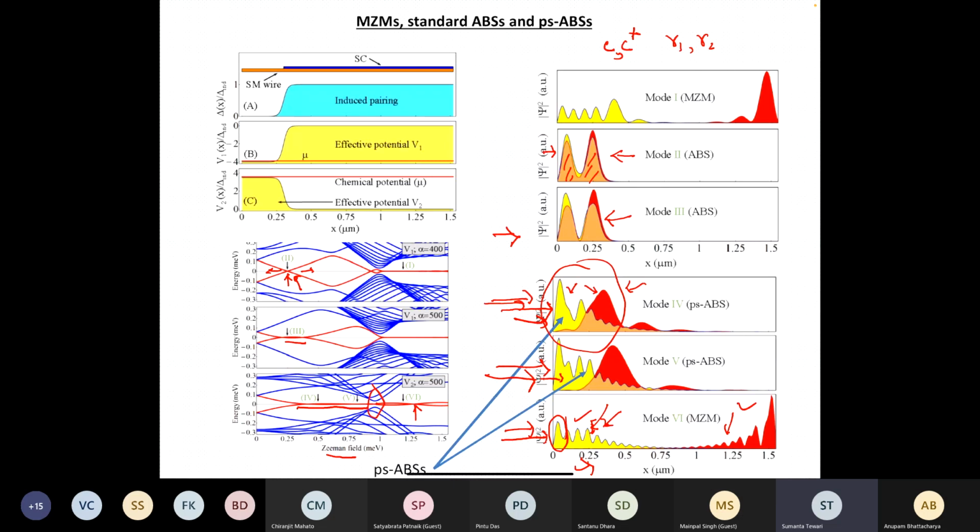Well, that's a good question. In fact, that's an interesting point. So you are saying that the muon spin rotation experiment, which I thought is in fact a bulk probe, is a surface probe. Yeah, and you can grind it. You can have small grains of the crystals. You can grind the sample to about 2 micrometers, typically the coherence or penetration depth range, and thereby increase the surface to volume ratio of each of your particles where the muons are getting embedded, and therefore you dominantly get the surface contribution only.